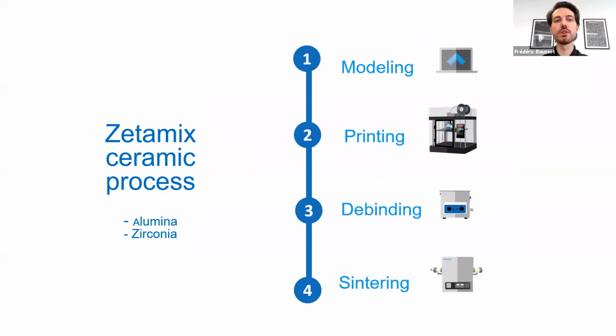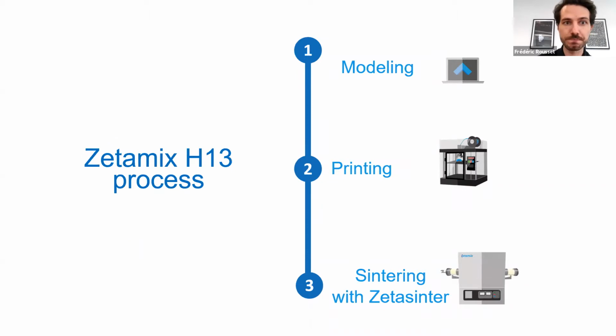So I'm going to develop a bit more on the different processes depending on the material that you have. For the ceramic, so alumina and zirconia, you have 4 different steps: the modeling, of course, then the printing, then a chemical debinding that you have to do. And after that, you have the sintering. So for the sintering, it is in the Zetamix, which is working very well for all of our ceramic.